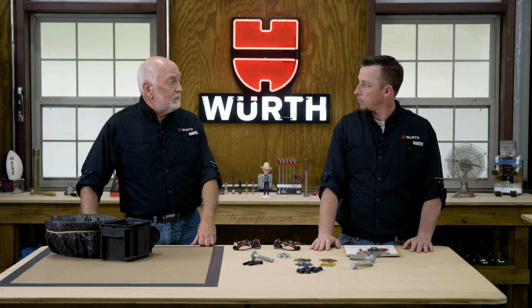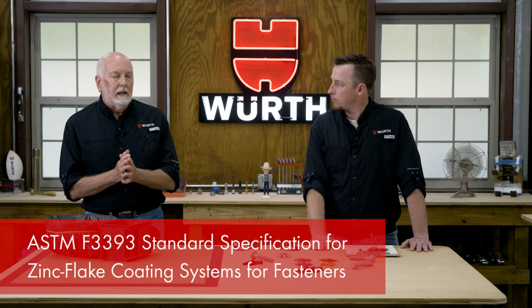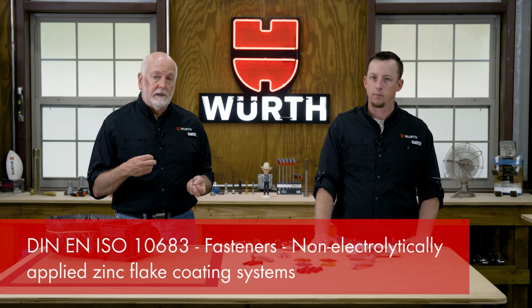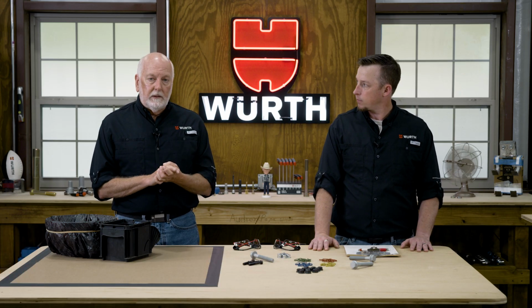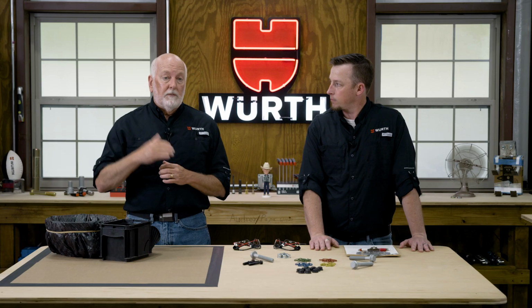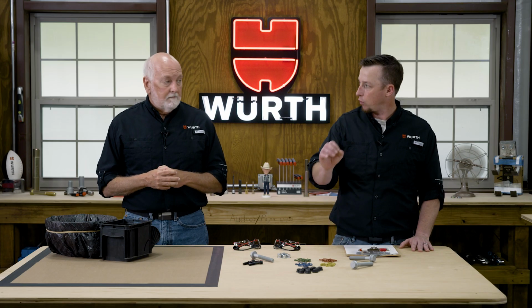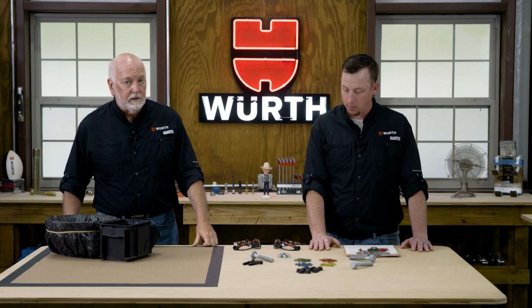ASTM has covered this now with a brand new specification. Yeah, ASTM F3393. That spec just came out back in August. And by the way, the ISO specification for metric is ISO 10683. But in the ASTM F3393, they gave you different codes. We have a code for what corrosion resistance you want. We have a code for what color you want. You can see right here, these finishes come in different colors. And they have a code for the coefficient of friction. Yeah, you've got a plus or minus 0.04, which is awesome to help control that torque a little bit better when you're working with the torque-tension relationship, a much smaller scatter than we're seeing with other finishes. So we're very excited. Great job on that new specification.